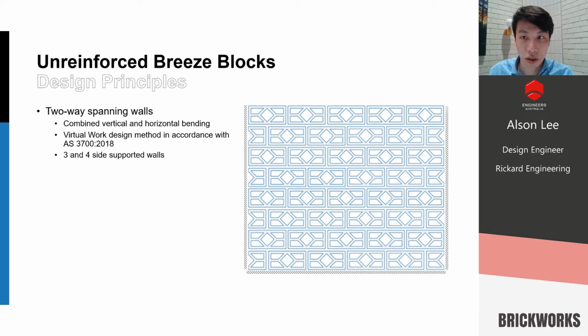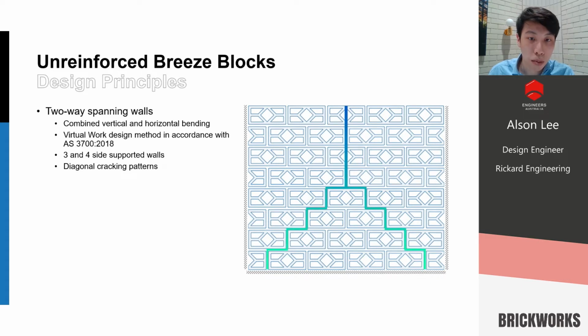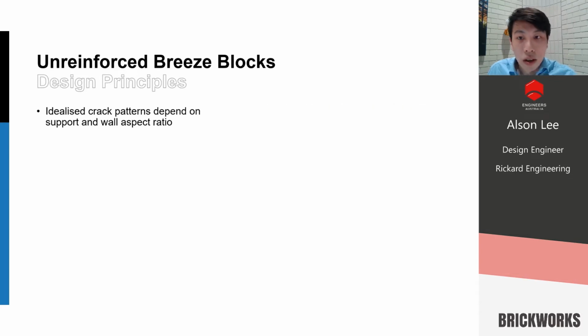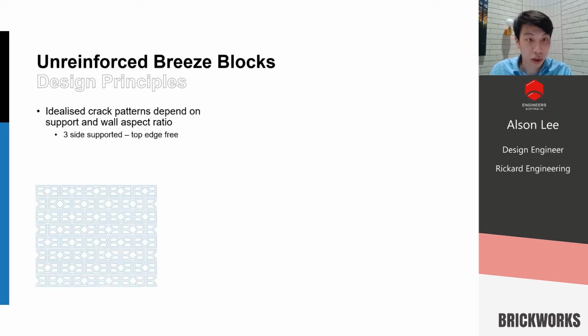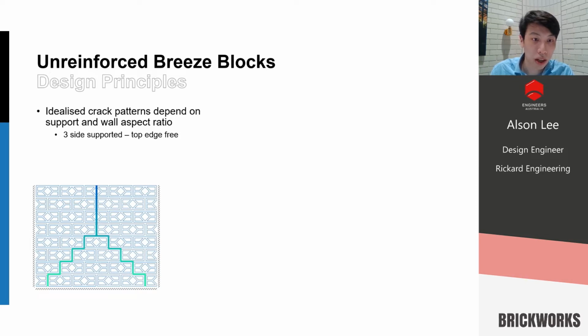Okay, so we have 3 and 4 side supported walls. And what tends to happen is that we get a more complex failure mode, namely diagonal cracking patterns in addition to the vertical and horizontal cracks. Our idealized crack pattern for our analysis will depend on our support conditions and our wall aspect ratio. As we've just gone through, for 3 side supported with the top edge free, we're expecting a failure mode similar to the diagram shown, with a diagonal crack and then a vertical crack splitting towards the free end.